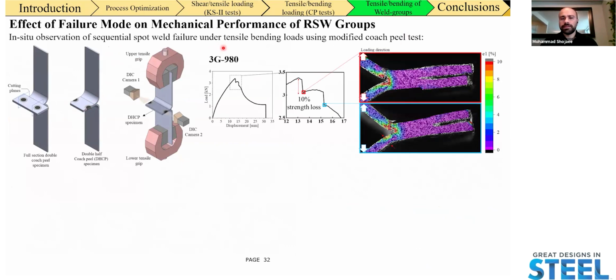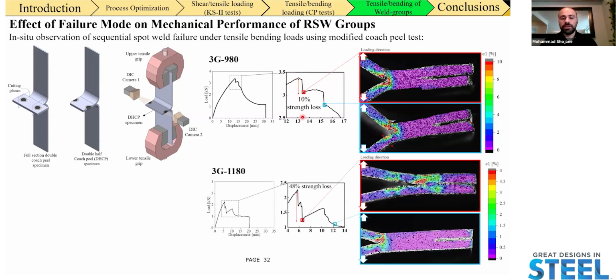What I want to highlight is that in the case of the 3G 980, consecutive failure under tensile bending loading conditions results in around 10% strength loss from the first weld failing to the second weld failing. But when we get our partial interfacial, partial pullout failure in the case of the 3G 1180, we're getting a much more catastrophic strength loss between the adjacent spot weld failures.